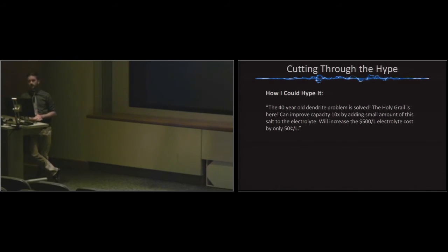So how would I hype this material? I would say something to the effect of the 40-year-old dendrite problem is solved, the holy grail is here. We can improve the capacity of our batteries by about a factor of 10 by adding just a small amount of this salt to the electrolyte. The electrolyte typically costs about $500 per liter, and this would only increase that cost by about 50 cents per liter, which is about 0.1%.